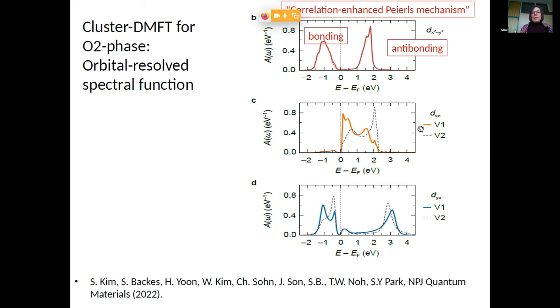the EG pi orbitals here do something more interesting. You see it here. So the XZ orbital is essentially empty, which means that the remaining electron goes into the YZ orbital, which is then half filled. And that means that here we are actually doing a Mott transition. So one orbital is correlation-enhanced Peierls, one is empty, and one is Mott insulating. And that after orbital ordering because of this effect here. So you can say you have it all in one, both a Peierls or correlation-enhanced Peierls transition and a Mott transition depending on the orbital.